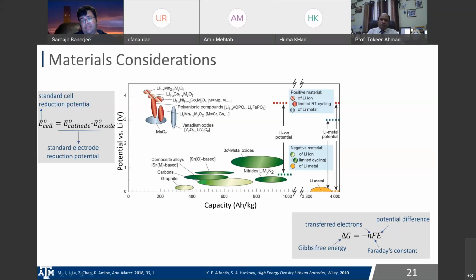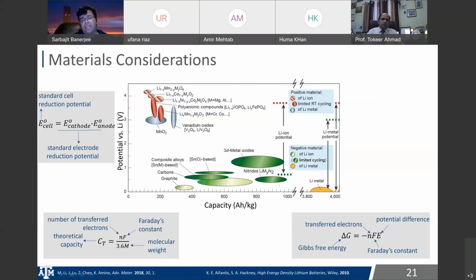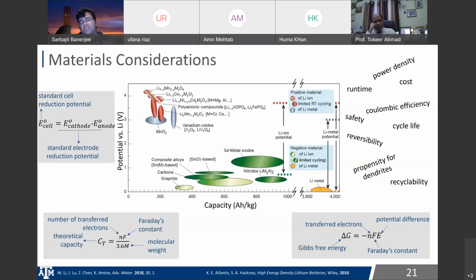So the lowest possible anode choice here is lithium metal, right? So why don't we use lithium metal? This has mostly been a problem with safety, right? The lithium forms dendrites. And again, there have been many companies and many academic labs that have tried to use lithium metal, and they've tried to get it to cycle and plate in the form of homogeneous uniform thin films. And it's been incredibly difficult because some fraction of times it does not plate as thin films. It forms dendrites, and those dendrites will essentially short circuit the battery and get thermal runaway going, which results in all these large battery fires you see, or just the battery completely dying, right?